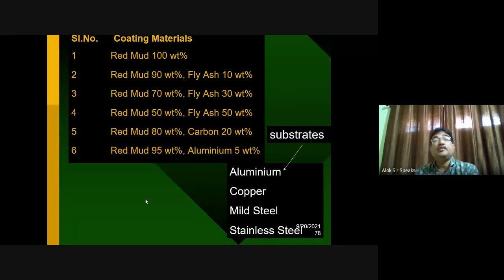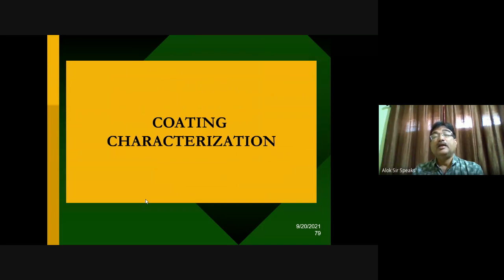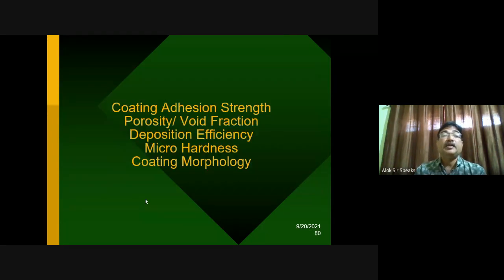You can see that we tried red mud 100%, red mud and fly ash in 9:1 ratio, and red mud and fly ash in 7:3 and 5:5 ratios. Then we mixed a little bit of carbon powder with red mud, because carbon is a reducing agent. And red mud was also mixed with 5% of spray grade aluminum, just to see how it affects the coating properties and coating quality. We tried different substrates, because the coatability of a particular coating material cannot be the same on all metals or all surfaces. The mechanical anchoring depends on the nature of the substrate as well as the nature of the coating material. So to see that variation, we tried aluminum, copper, mild steel, and stainless steel surfaces, and we coated them using a plasma spraying technique.